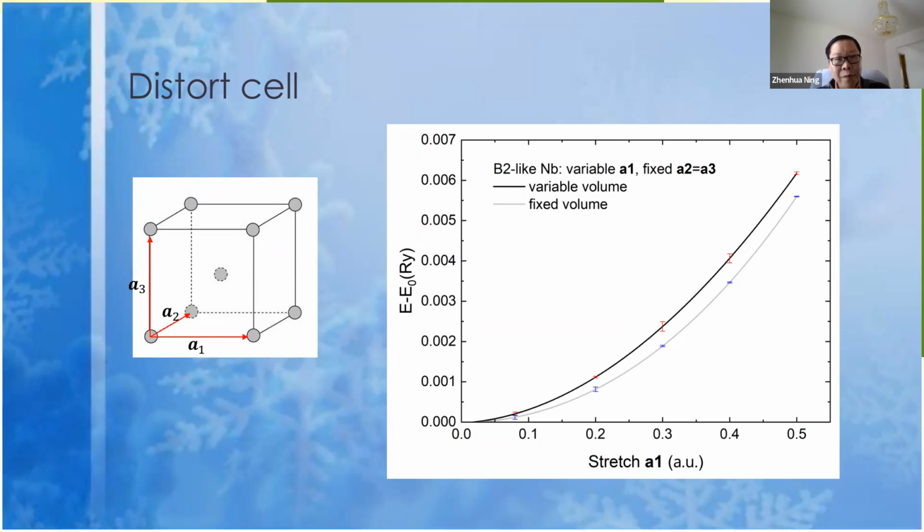When we calculate force, say if we displace the atom, this could cause the R mesh to be unstable, and it can cause trouble for the force calculation. Okay, are you talking about the radial R mesh? Yeah, the radial R mesh. So in other words, the result is very sensitive to the gridding and the angular momentum cutoffs and so forth as you try to displace an atom to get forces. That's my takeaway. Yes.